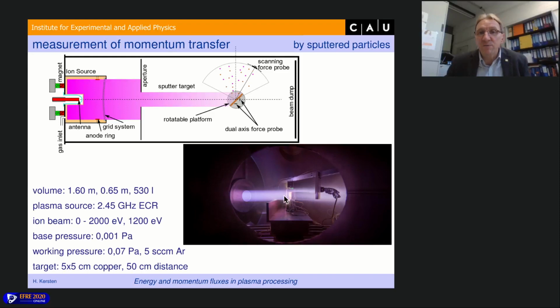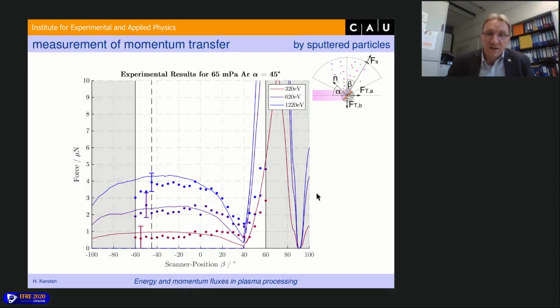So we have here our ion beam, as you can see here. And here we can rotate our probe surrounding the target and measure the incoming force. And here you can see this is the scanner angle. That means the angle of our force probe surrounding the target. This is the substrate. And alpha is the angle of the incoming ion beam to the target. And as you can see here, for instance, we have here an angle of 45 degrees of the target to the ions.